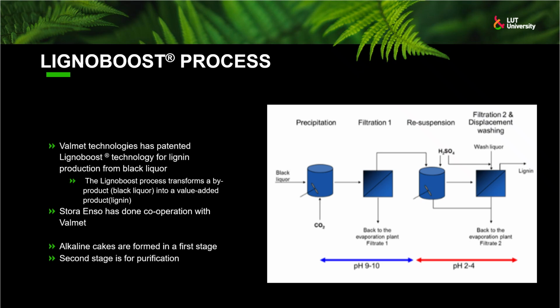In the first stage, carbon dioxide is used to decrease the pH. Formed alkaline cakes are re-slurried with sulfuric acid. Acidic slurry is filtrated and purified cakes are washed twice, first with sulfuric acid solution and finally with water. In this thesis, the LignoBoost process in laboratory scale was used to precipitate lignin from black liquors.